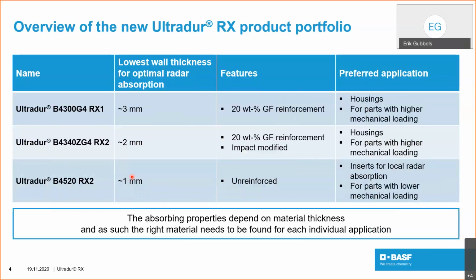Here is an overview of the Ultradur RX product portfolio, RX standing for radiation extinction. There are 3 materials in this portfolio. First, the B4300G4 RX1, meaning the first generation radar absorber. Secondly, the B4340ZG4 RX2, where RX2 indicates the second generation material. At the end, there is the Ultradur B4520 RX2. Even though all these materials are good absorbers for electromagnetic waves, they have different lowest wall thicknesses for optimal absorption. As you can see, this optimal wall thickness decreases from 3 millimeters in the first generation to 2 and 1 millimeters in the second generation.